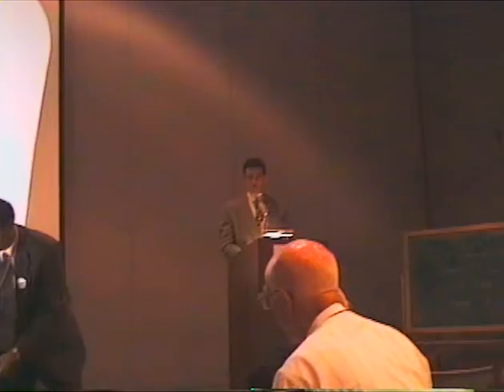One last one. Chang from Mobil. Gary, can you explain why the activity levels are? I think it's because the metal is on the exterior part of the zeolite, and we know that those type of sulfur concentrations, if you're on an amorphous binder, I believe there's a small fraction of the metal that's there that gives you constant activity. It has nothing to do with the activity of the zeolite. Because I try to be careful when I'm saying that, because you see that baseline deactivation, why doesn't it go to zero? I think it's because it's on the amorphous binder.